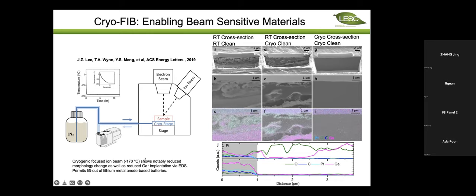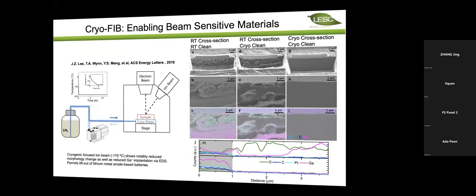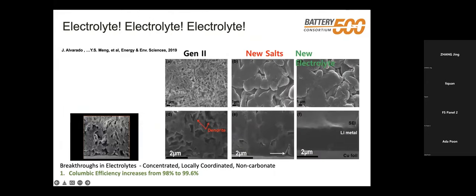And this fit, the cryogenic focused ion beam fitting, can be done easily, retrofit in your machine. And so we will be able to preserve the original state of the lithium metal. And this becomes particularly important if you're studying electrochemically deposited lithium, because the morphology can change drastically based on the electrolyte solvent, the salt that you're using.